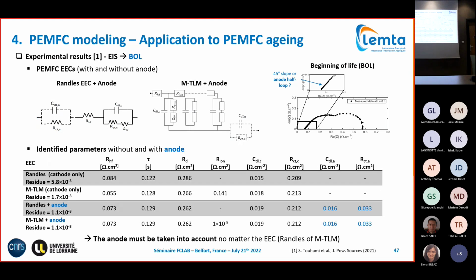So, to answer the question for the beginning of life, we tested a Randles circuit, an interfacial electrode with an anode, and a modified TLM, thick electrode, with an anode. Here you see all the parameters identified with the configuration without the anode, so without the dotted lines, the Randles and TLM circuits. You see we have different parameters, and here a contribution of ion conduction through the cathode volume of the electrode. It is difficult to say which one to use. The Randles circuit did not yield really satisfying quality for the 45-degree loop.